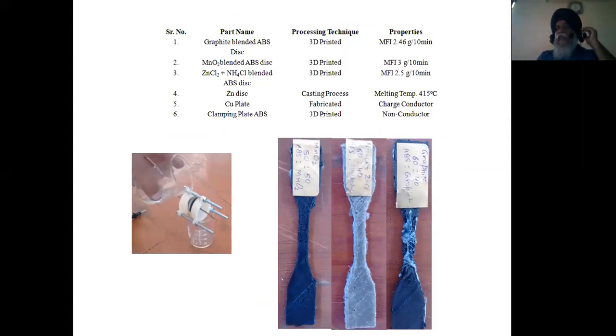So suddenly we got an idea that there may be some hindrance in the flow of the charge, because resting is common in the conventional cell, or the conventional battery. So what we did, we took acetone, because acetone can dissolve the ABS, and we just poured the acetone on this, and then we measured the voltage, and to our surprise we were able to get a consistent 1.5 volt as an output, right? So this is really good.